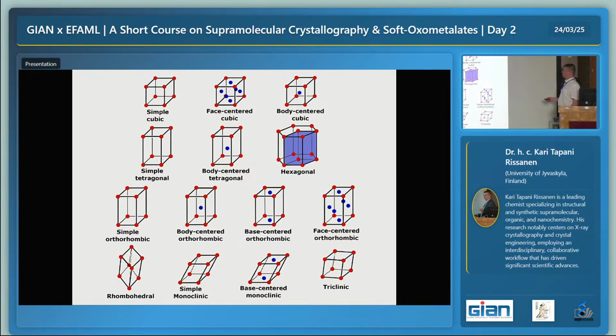In tetragonal we can have two choices, because now A and B are the same, so you cannot have it on the face; you can have it only in the body, in the center. Hexagonal is like rhombohedral and triclinic, where the only possibility is the hexagonal primitive one.